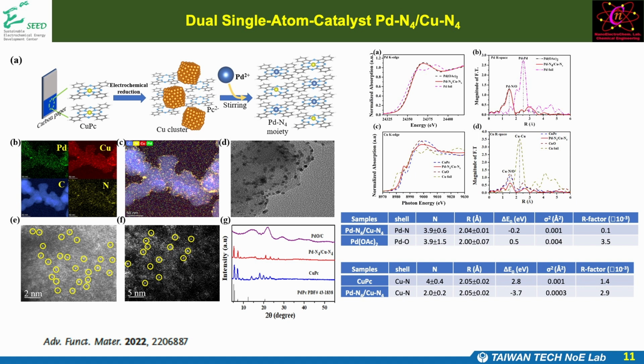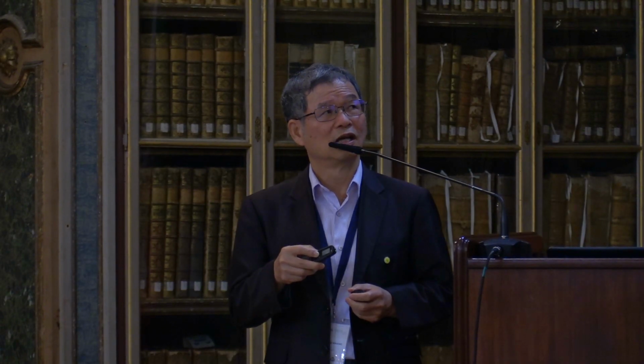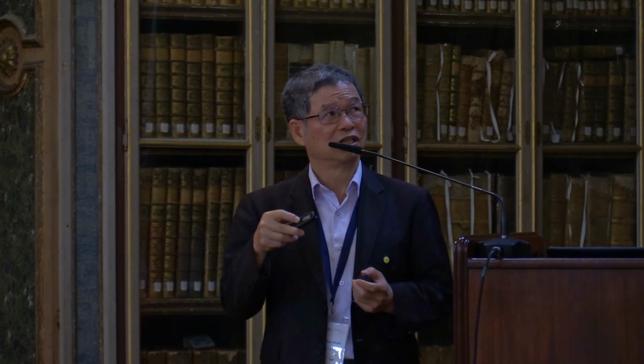Like this example, we use palladium to do the replacement. Then we can produce the dual single atom with the palladium and copper single atom. Again, we confirm by X-ray absorption and also high resolution TEM. We can confirm we can get this dual single atom, then apply in